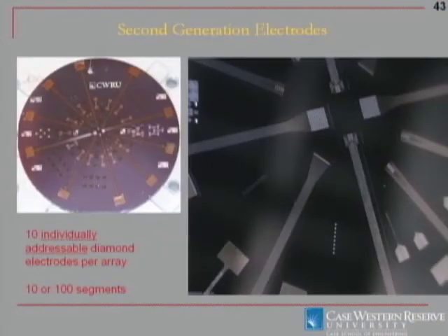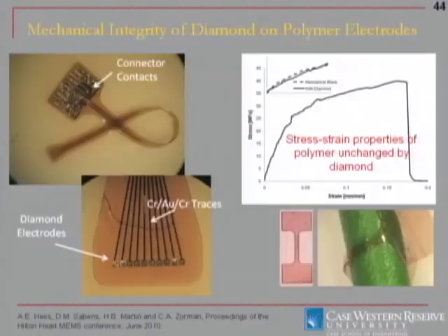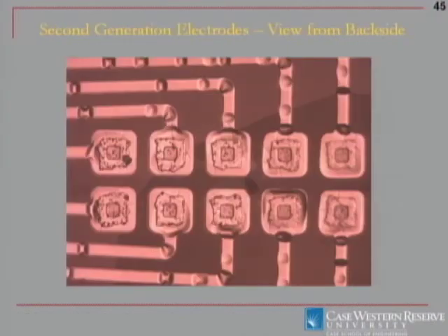And this shows that we can bend this in the bottom of a cell. We've moved on, of course, to a much more microfabricated process where we're making 10 individually addressable electrodes. This is a segment electrode of 10 segments per electrode. And with that, we end up with these. We have 10 diamond pads here, each individually addressable with a nice bendable lead, a chromium gold chromium trace. Mechanical properties of the polymer are not really impacted by having these very small diamond pads incorporated in them. This is just a picture of those showing the multiple layers.